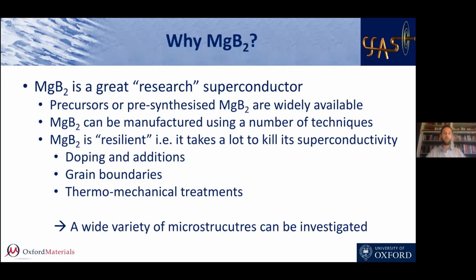But the most important thing, I think, for research in MgB2 is the fact that it's very resilient. And by that, I mean, it takes a lot to kill its superconductivity. And this is in sheer contrast with the talk we've seen just before. In HTS, we can see that if you have a little bit of misalignment, it doesn't really like it. In MgB2, actually, you can do a lot with it. So you can add grain boundaries. You can actually have a lot of grain boundaries. MgB2 quite likes it. You can add a ton of stuff: doping with carbon, any kind of oxide, nitride additions, and it still superconducts. And obviously, you can also do a lot of thermomechanical treatments. So it's a really interesting material because you can generate a wide variety of microstructures, and then you can investigate how these might be beneficial for the properties.